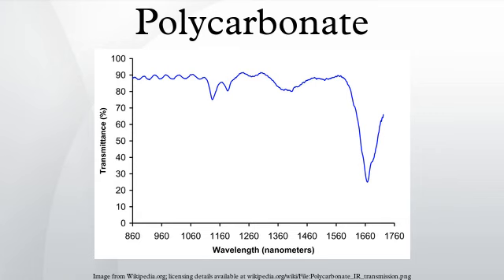Bisphenol A appeared to be released from polycarbonate animal cages into water at room temperature, and it may have been responsible for enlargement of the reproductive organs of female mice. However, the animal cages used in the research were fabricated from industrial-grade polycarbonate, rather than FDA food-grade polycarbonate. An analysis of the literature on bisphenol A low-dose effects by vom Saal and Hughes published in August 2005 seems to have found a suggestive correlation between the source of funding and the conclusion drawn. Industry-funded studies tend to find no significant effects, whereas government-funded studies tend to find significant effects.